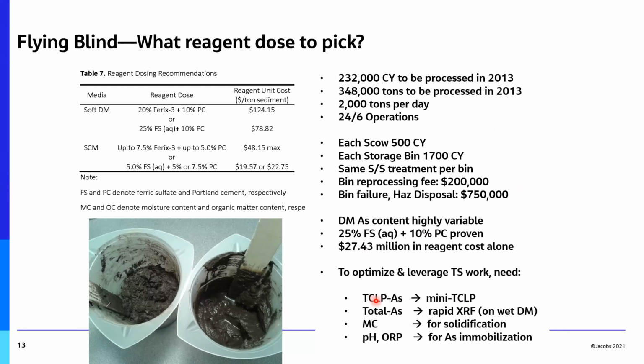So what we took a look at was, we're being regulated against the TCLP arsenic. We can collect totals information as well to help us understand how contaminated it is. Moisture content, that's a quick test. pH and ORP are also very quick tests. So the real logjam here was the TCLP test, which is usually an 18-hour extraction. So we devised a mini TCLP that we could use on-site with an on-site lab and do a rapid turn on that, so that in the decanting period, which was 6 hours for each scow to let the water come off, we would have a result and be able to say, hey, this is what dose you should apply to that scow on a real-time basis.